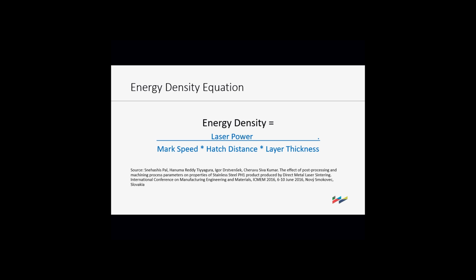Okay. And so one of the things that I was involved in, teaching at UTEP and working with their facility in 3D printing, people, I think they were in Slovakia, came up with laser power over scan speed over hatch distance, and layer thickness is how thick you melt it to. And so that seems to work in a lot of predictions fairly well.